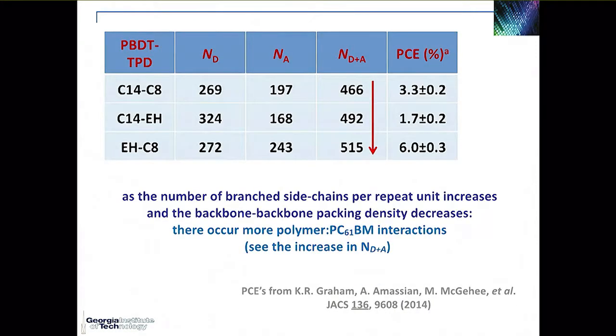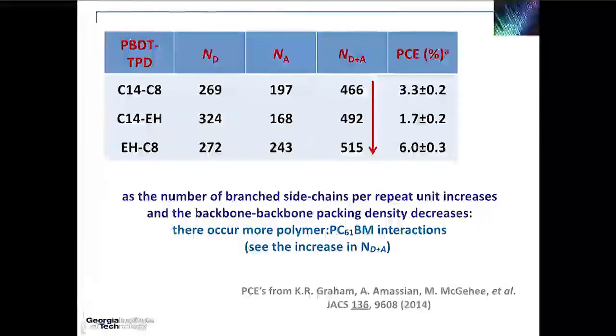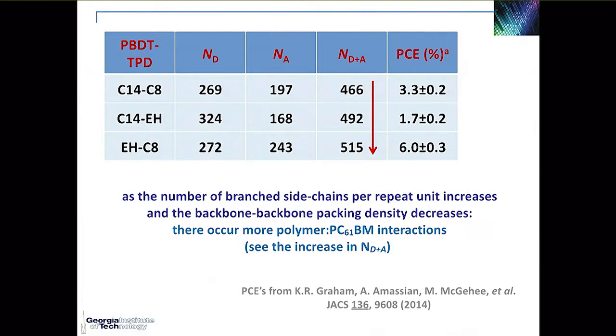And that's actually what we see. Let me just tell you what this table is about. We are looking at the 3 different polymers. We have in the simulation box exactly the same total number of fullerenes, and those capital N values refer to the number of fullerenes that come next to the donor or the acceptor, and the total number of fullerenes that are in interaction with the polymer chain, so the sum of the first 2 numbers. And what we get is, as the number of branch side chains on the polymer increases and the backbone packing density decreases, you get a larger number of polymer-PCBM interactions. So that's, I think, pretty logical.